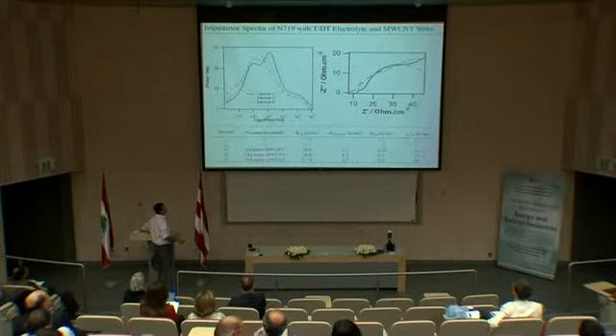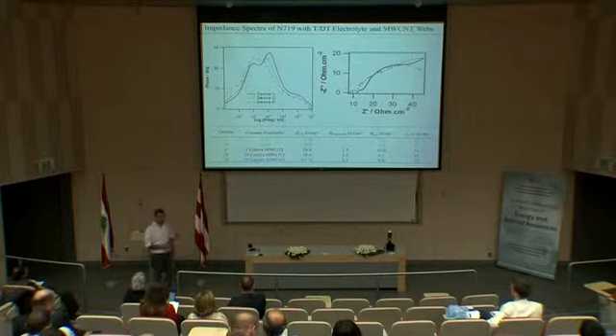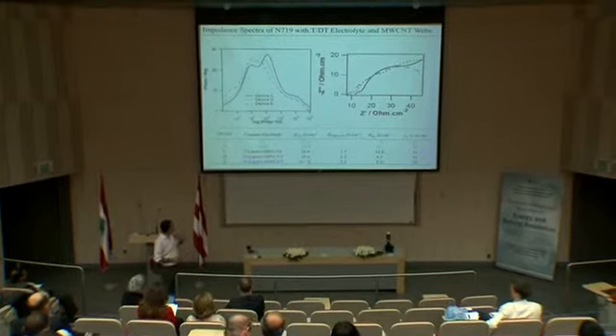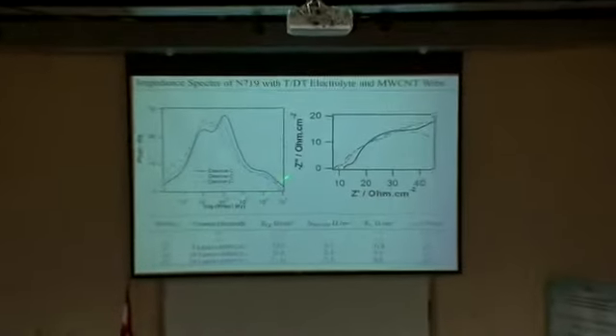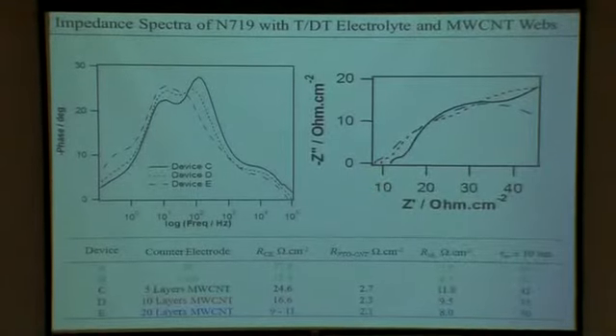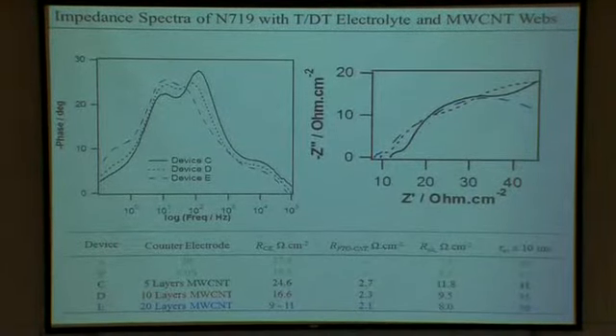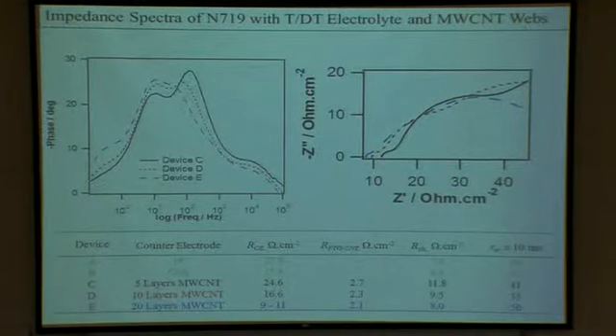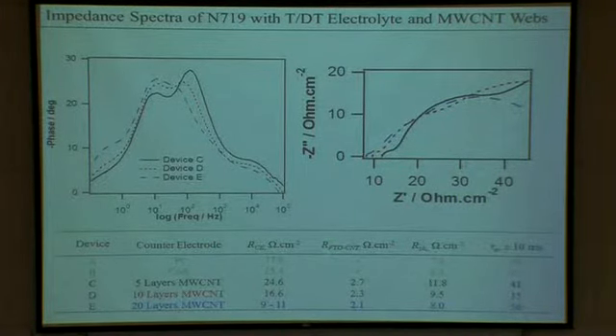We are still working on the long-term stability of this new electrolyte. I just want to mention a little thing here: as we increase the number of layers, the series resistance in the solar cell diminishes. So as we go to the 20 layers here, the series resistance went down from 12 down to 8 ohms per centimeter squared.